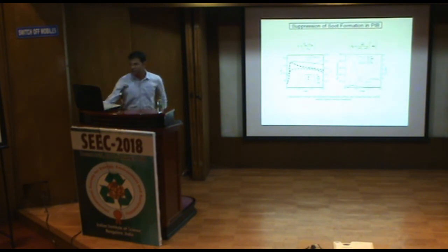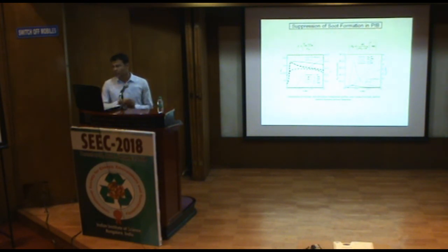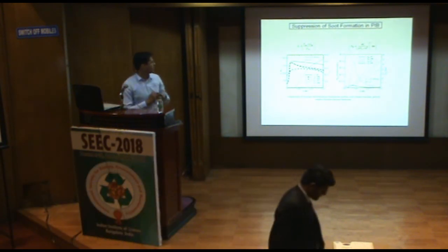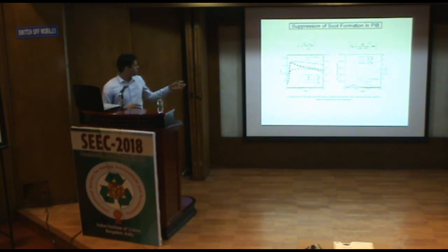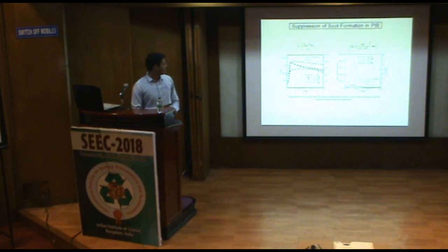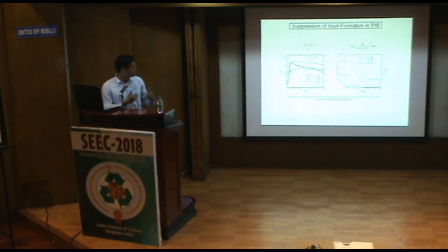Here the comparisons of axial gas and solid phase temperature profiles and soot governing parameters like soot volume fraction, particle number density, and soot particle sizes are plotted along the axis. Here you can see that for the porous burner, the gas phase temperature decreases rapidly as compared to free flame. The lower temperature in the post-flame region hinders the soot growth process. Also, in the porous burner, soot inception initiates at a later stage as compared to free flame. The soot particle number density is less, and the particle diameters are also smaller than those of the free flame.